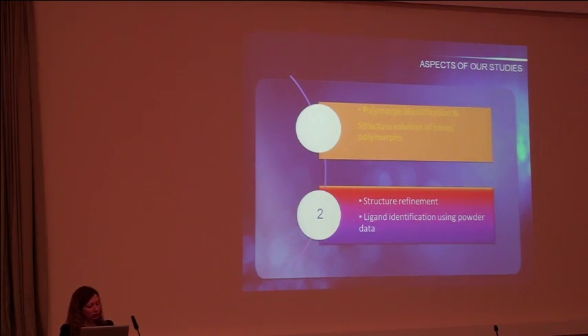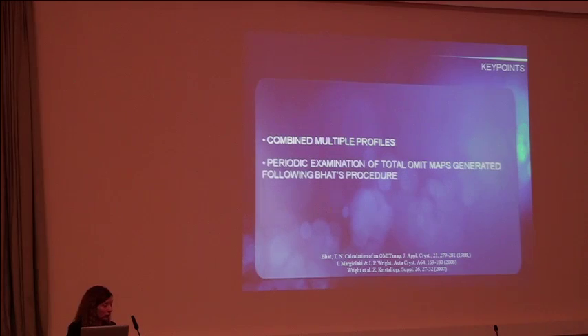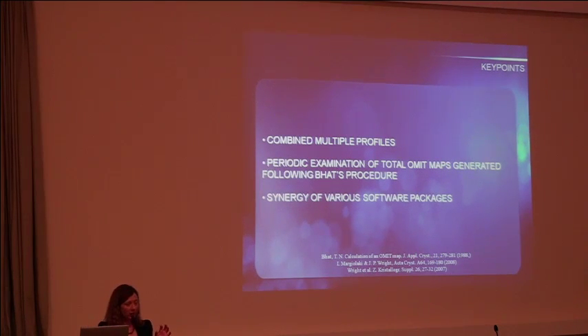Finally, I would like to show that we don't just do indexing. With good data, you can really solve structures and refine, but there are some tricks. You cannot refine a large structure using only one profile because one powder data set does not contain sufficient information. So we use combined profiles, and our methods are described in these 3 articles in order to enhance the information content. We use total omit maps, better than difference electron density maps, because they have less model bias.